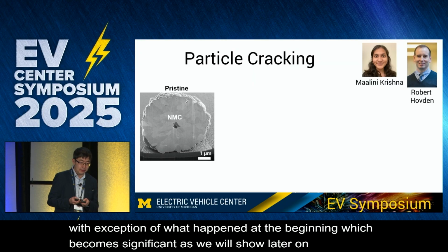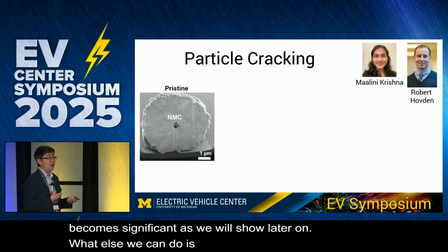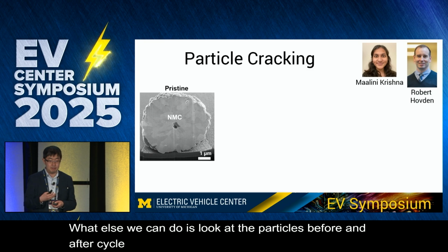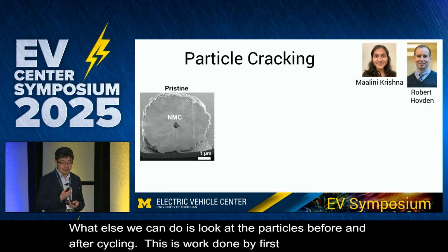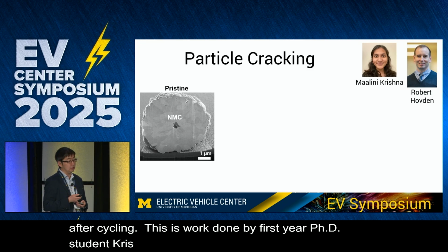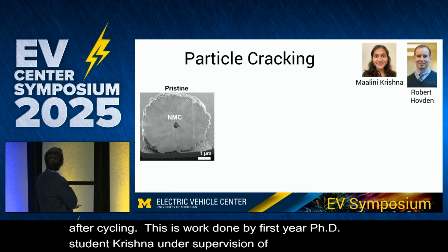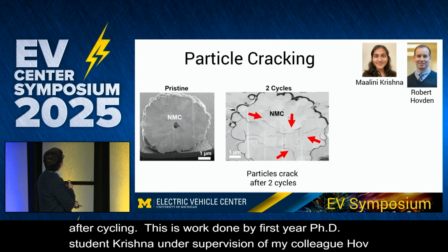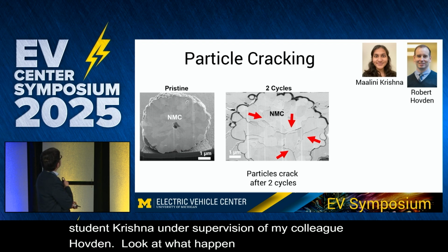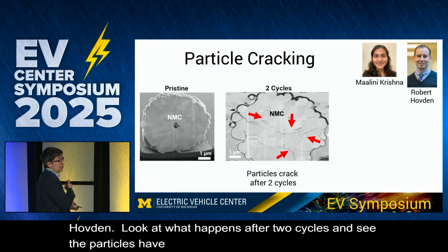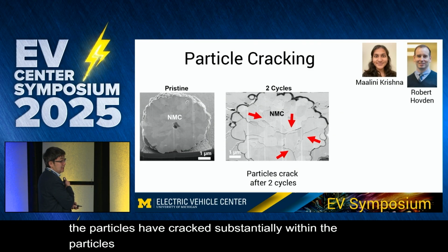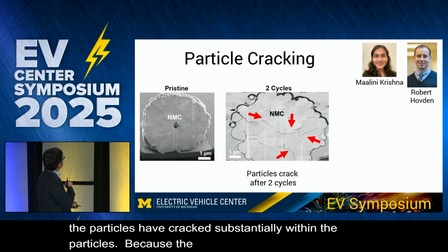What else we can do is we can also look at these particles before and after cycling. So this is work done by a first-year PhD student, Maalini Krishna, under the supervision of my colleague Robert Hovden. So you can look at the pristine particle on the SEM here. Then you looked at what happens after 2 cycles, and you can see that these particles have cracked substantially within these particles. So because the electrolyte is a liquid, we can infer that probably the liquid can infiltrate into